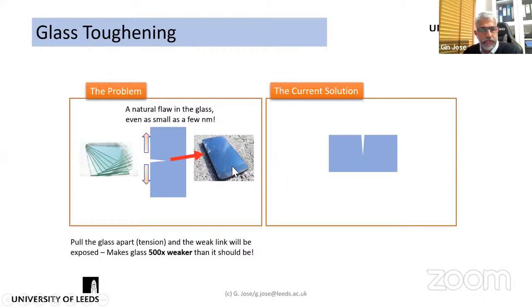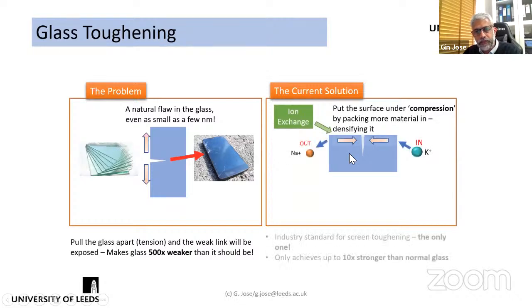Another application that we are looking at is strengthening of the glass surface. Currently, most mobile screens are made of toughened glass, most of it produced by Corning under the brand name Gorilla Glass. The toughening process works by introducing potassium into the glass by replacing sodium. Potassium is a large ion compared to sodium. So it's a chemical process where you replace the sodium with potassium. You essentially create a stress layer at the surface, which provides the strength to the mobile glass screens in the current ion exchange based process.